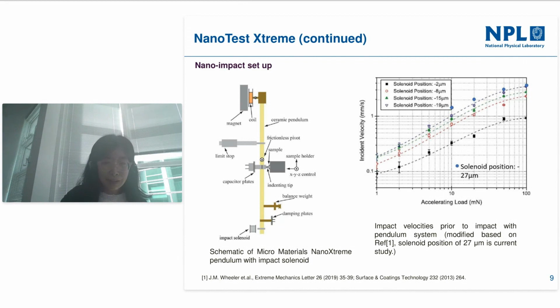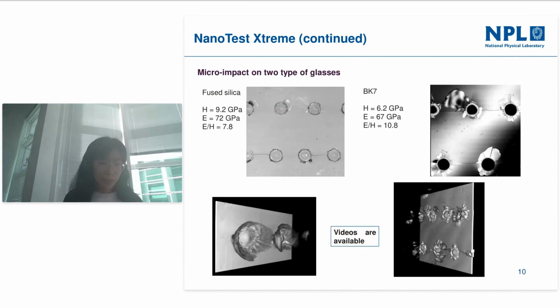So the next slide is an example of the micro impact test on different types of glasses. There are two types of glasses, fused silica and BK7, with different hardness and modulus values. And you can see the fracture pattern in fused silica is a cone shape, while in the BK7 it's like lateral micro cracks underneath the indent and radial cracks on the surface. These images were taken by laser confocal microscope, which gave us a depth profile of the transparent glasses.